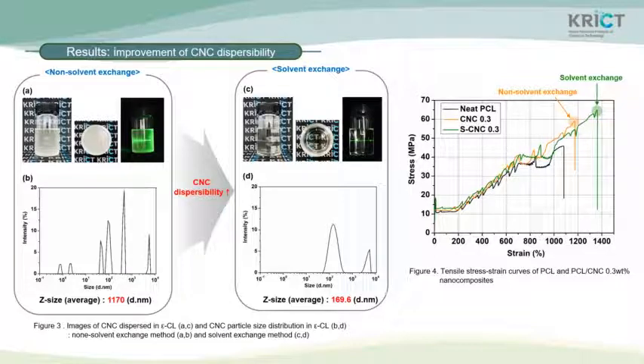Through this process, CNC dispersed in acetone can be obtained. Acetone, which is the CNC dispersion solvent, can be replaced by another organic solvent without phase separation. With this method, CNC dispersibility much improved, as you can see in figure 3C. Also, CNC particle size in the dispersion solution decreased through solvent exchange method in figure 3B and D. As a result, we can see the tensile toughness increased in figure 4.